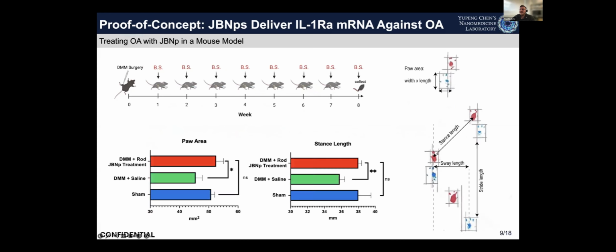So the first part of the behavioral study consisted of a gait analysis where we tracked the gait of the treated and untreated mice. We then made measurements of their paw area, stance length, sway length, and stride length. And what we saw was that in groups treated with JBNP, seen in red here, their paw area and stance length were much higher and more similar to the healthy control groups than that of the group that didn't receive any treatment at all. And this tells us that the mice treated with JBNP maintained a very healthy gait pattern and therefore were not experiencing pain or immobility from cartilage degradation.